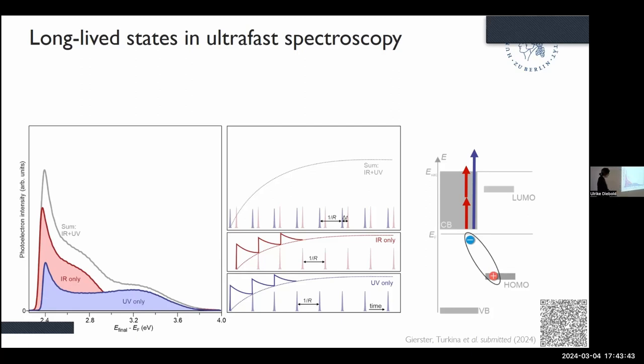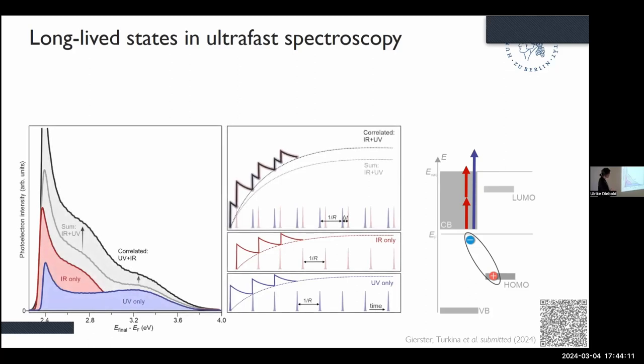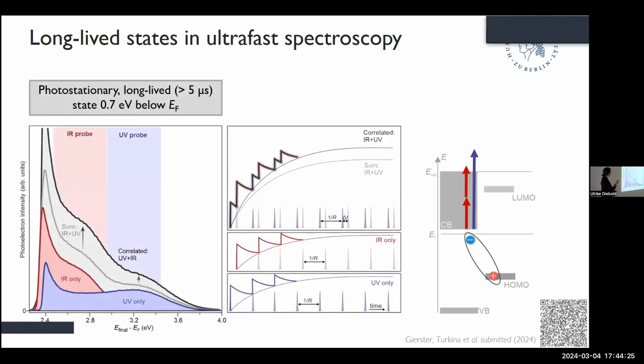A first step to show this is to compare the IR and UV only spectra, take the sum of them, and compare it to the situation where you have both photon types on your sample. Because if there is a correlation and a photostationary state being built up, you will come to a different intensity, because you have a correlation between the laser pulses. And this is what we observe. We see a quite substantial increase of the signal if we have both colors there at the same time. So it's not just a simple occupied electronic state. So we have a photostationary state. It must have a lifetime larger than the 5 microseconds repetition rate in our experiment.